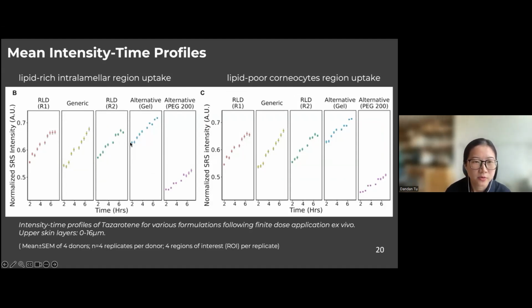And for all the 5 test groups, those are the intensity time profiles. The reference listed drug and the generic drug have very similar intensity profiles. For the alternative formulation, the gel formulation, the intensity is slightly higher than the generic drug and the reference listed drug, indicating a slightly higher amount of drug present in this treatment group. And for the alternative formulation PEG 200, it shows a much lower intensity, indicating a lower amount present.